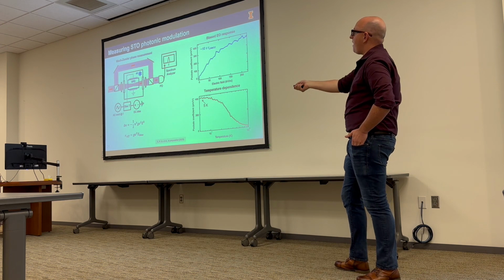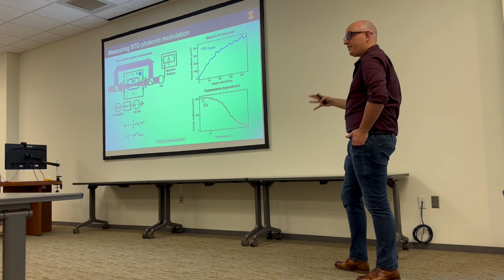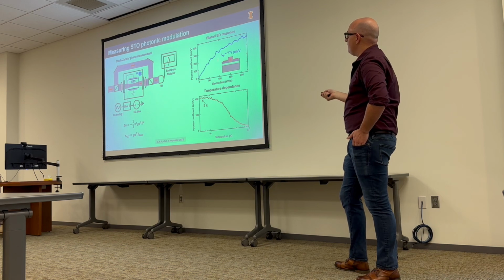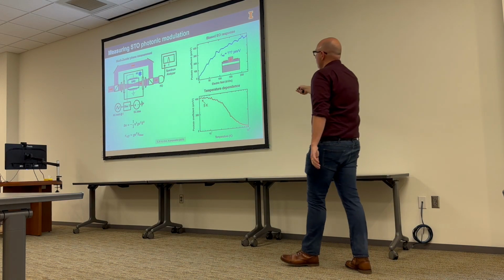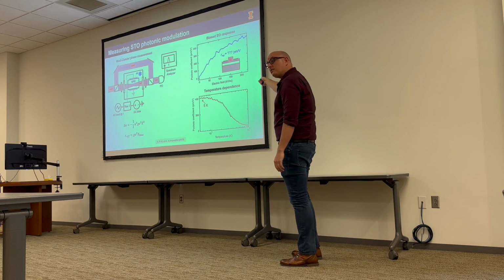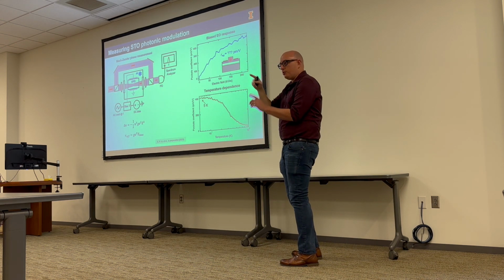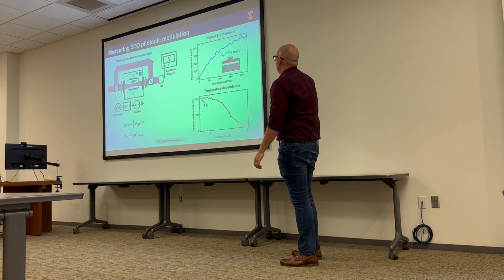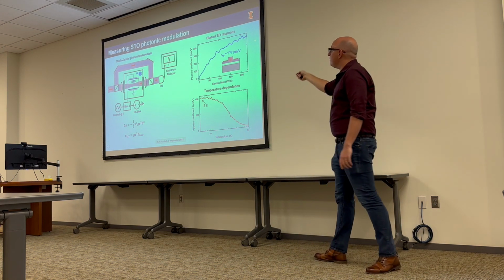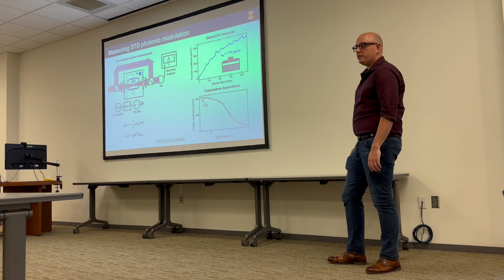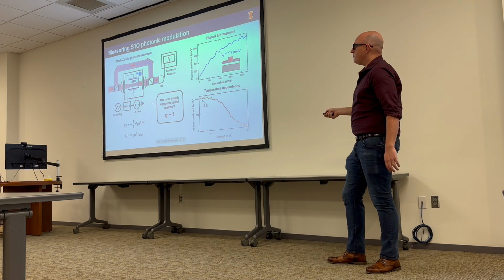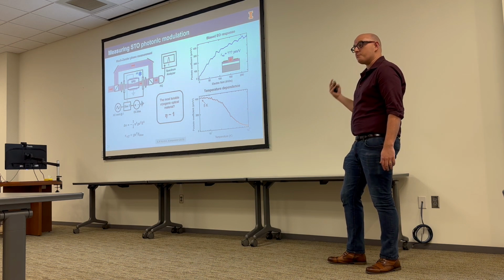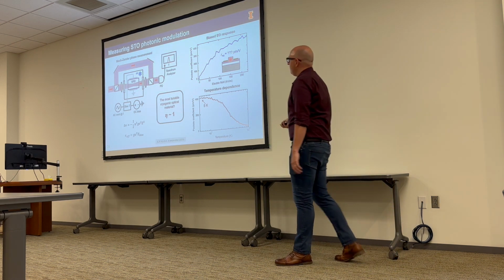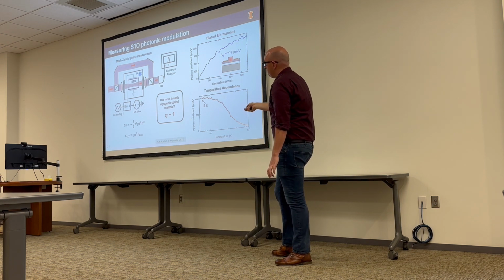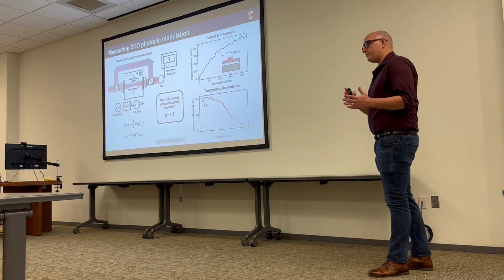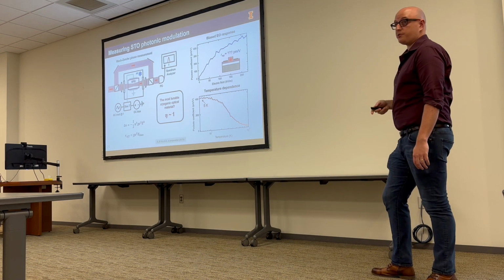But of course, having a 1 millimeter crystal with a DC power supply across it is not the end goal here. The end goal here is to have some lithium niobate-like integrated photonic chip, where you have electrodes that are biasing the system, but not over 1 millimeter, but over something like 5 or 10 microns. And so we actually don't know, when we bias more and more, what the ultimate limit of this nonlinearity will be. So we've already measured something that's the most cryogenically tunable optical material that's ever been measured. It beats lithium niobate, barium titanate. We don't know how high it will be. We really think that we can start pushing towards this transduction dream of microwave-to-optics at low temperatures with efficiencies that approach something like 1.